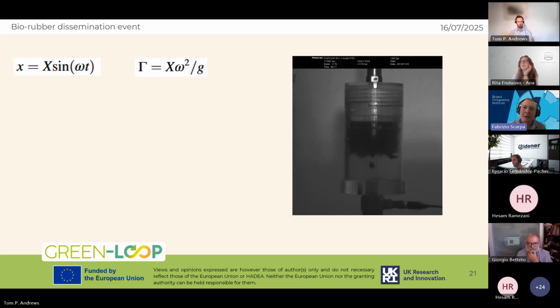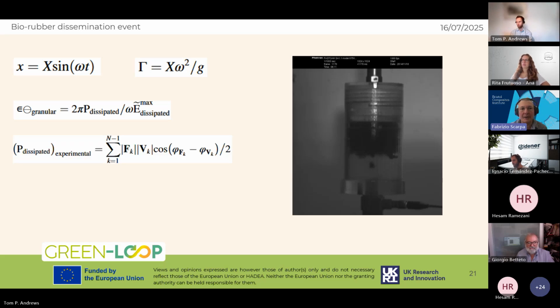I'm really sorry for the equation that you will see in the slide. Unfortunately, sometimes we need those. So you imagine that you have a sinusoidal type of excitation given by the sine function, and you can quantify a normalized maximum amplitude displacement based on the acceleration and the displacement imposed. This is gamma. We then define an efficiency of the energy dissipated by the damper, this epsilon granular.